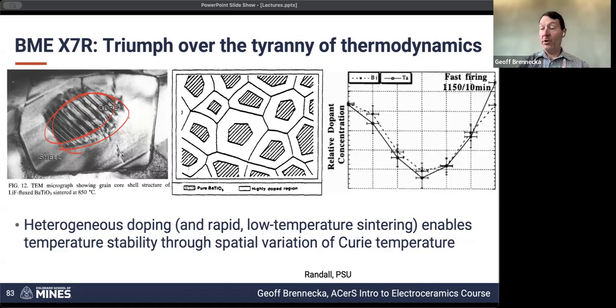For lead titanate, pure lead titanate, that strain is about 6%. And so lead titanate absolutely will crack and fracture when it goes through that, or it can, when it goes through that phase transition. Barium titanate is not so bad. So that's one of the reasons that barium titanate is so useful, is that we're able to get away with the domains that form accommodating that strain. So hopefully that helped.